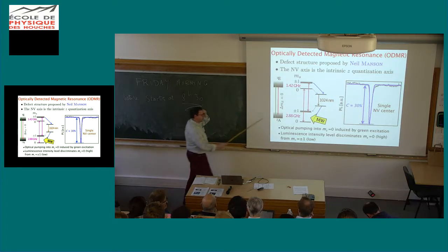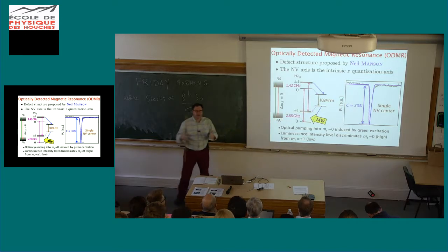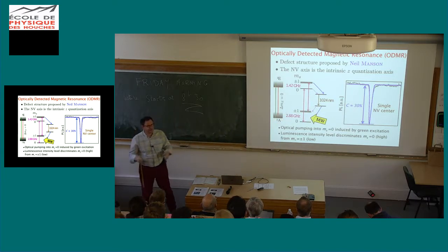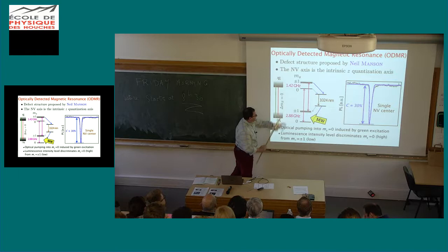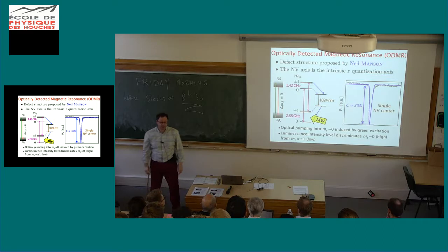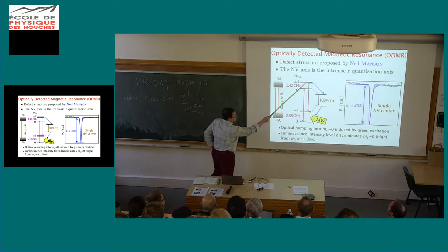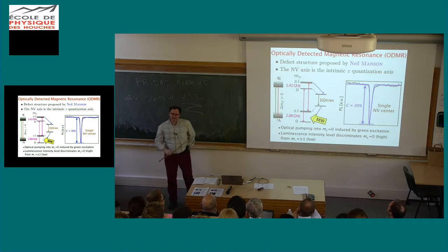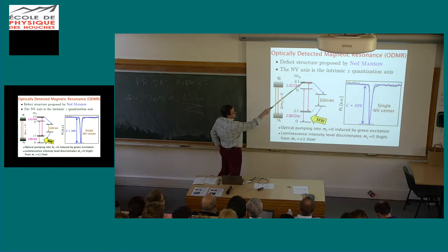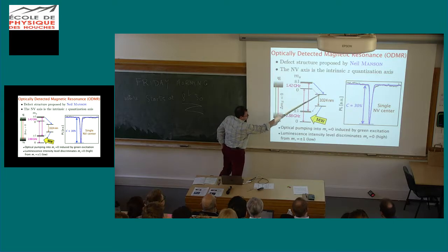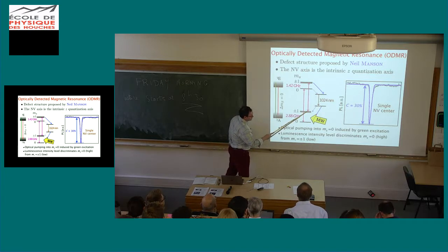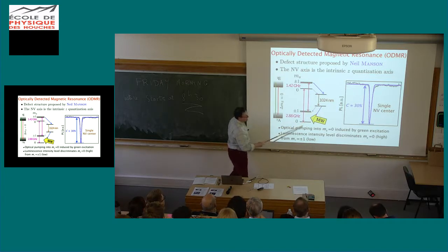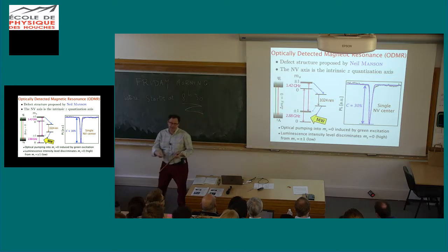But there is also the singlet structure corresponding to the addition of the 2 spin 1/2 of the 2 electrons in the atom. This is a metastable state, whose levels are connected by electron-phonon interaction to the excited state, but only ms plus minus 1 is connected toward that level. This means that if I now excite the NV center on this level, it has a chance to go to this level, and from there it will decay back both to ms equals plus 1, but most probably to the ms equals 0 state. So you see that you have an optical pumping scheme.